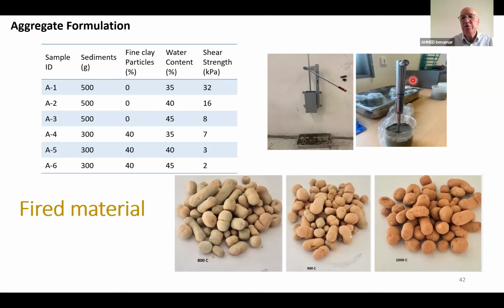So we used the vane apparatus to measure these values of shear strength, and we see that when the water content increases, the shear strength decreases consistently. For the fired materials, there are three firing temperatures: 800, 900, and 1000 degrees, which show that the color can change because of oxidations and modifications of mineral phases in the material during firing.